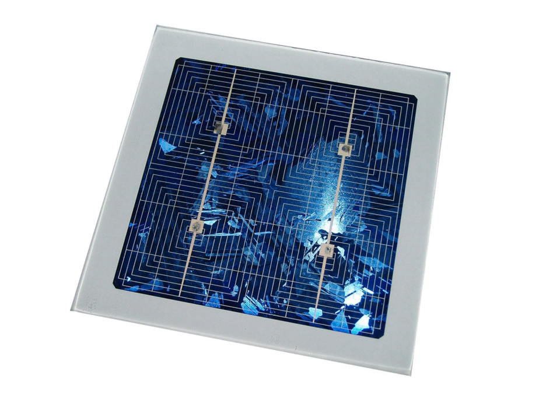However, organic solar cells generally suffer from degradation upon exposure to UV light, and hence have lifetimes which are far too short to be viable. The bonds in the polymers are always susceptible to breaking up when radiated with shorter wavelengths. Additionally, the conjugated double bond systems in the polymers which carry the charge react more readily with light and oxygen. So most conductive polymers, being highly unsaturated and reactive, are highly sensitive to atmospheric moisture and oxidation, making commercial applications difficult.